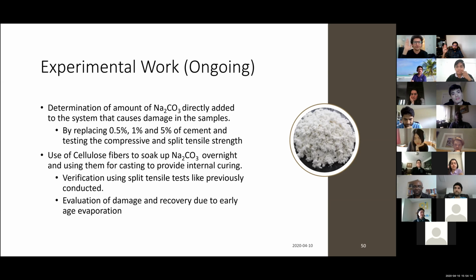Any other questions? Yeah, Shubham. Thank you for the presentation, Anupam. There are a few questions that I need to ask. Basically, you are adding sodium carbonate, like you are soaking your material with sodium carbonate, right? In the last test with the fibers, in the other ones, I either put them in the mix once just to see what the effect is, but usually I cure the samples in sodium carbonate water, so it's coming through the water into the system. Have you quantified if any sodium phase reacts with one of the cement hydration phases?